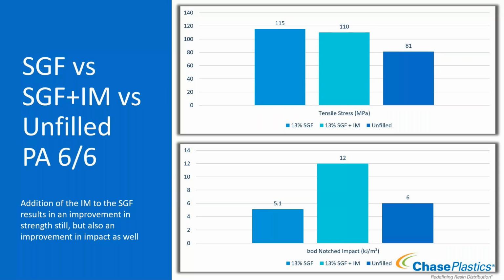But then you look at the big change down below, which is your impact. Your unfilled grade is performing at 6 kilojoules per meter squared impact. Your glass-filled grade, showing the loss of impact, is 5.1. And then when you look at a glass-filled and impact modified grade, you're getting a combination of the two - your impact jumps all the way up to 12.